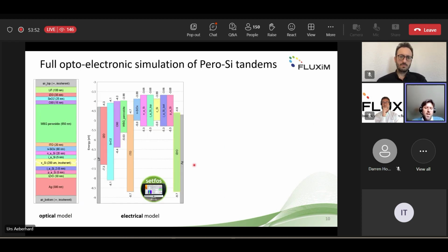So this is how we implement the full tandem structure electrically. There is a range of additional material parameters that need to be included now, in addition to just NK data and the layer thicknesses. Most importantly, the energy levels of the material, so the band edge energies for conduction and valence bands, or HOMO/LUMO, depending on whether you talk about inorganic or organic materials. But of course, there are also more parameters like mobilities, lifetimes, and so on.